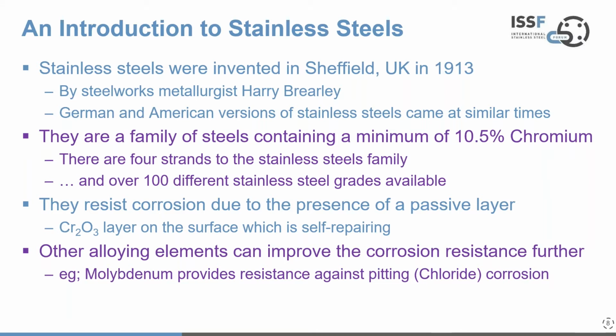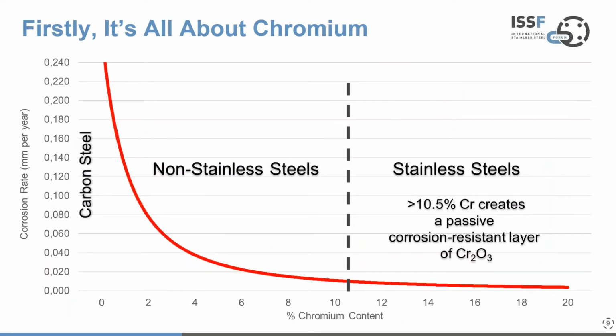They resist corrosion due to the presence of a passive layer, which I briefly mentioned. This is a chromium oxide layer on the surface, which is self-repairing in the presence of oxygen. And it's possible to increase the corrosion resistance further by adding further alloying elements to the analysis. Molybdenum, as an example, provides great resistance against a feature known as pitting corrosion, which occurs in chloride or highly oxidizing environments. So having set the scene, I'd like to talk about chromium, because from a corrosion resistance perspective, it's first and foremost all about chromium.